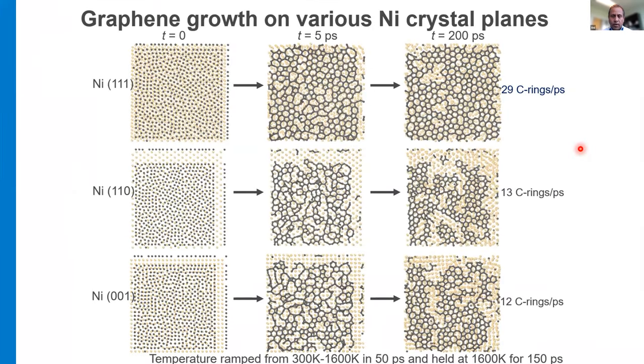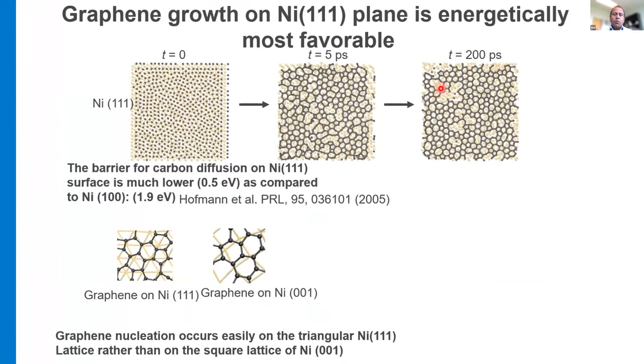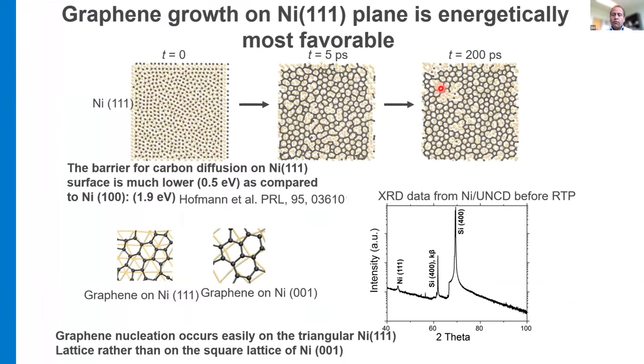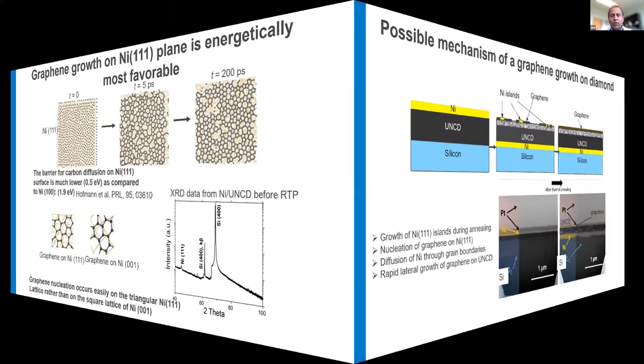If you look at the detailed molecular dynamics simulation that has been done on different phases and planes of the nickel, it looks like it favors nickel 111 in getting these carbon rings nucleated very fast. And when we looked at the nickel which is deposited, which has a 111 phase, we think that during the annealing process this nickel 111 phase grows even faster, and that basically forms the nucleation for the graphene.